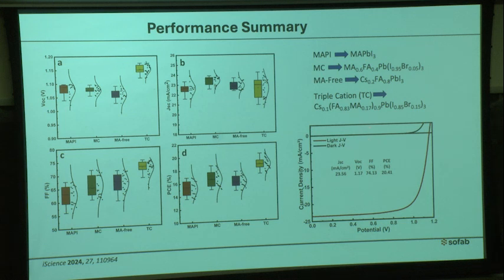Formamidinium will increase the stability towards moisture. If we add both cesium and formamidinium to the methyl ammonium, we can get perovskite with superior quality. That is due to improvement in quality of the perovskite, and we are able to get much higher power conversion efficiency as compared to other perovskite compositions. So MAPI means MAPbI3, and mixed cation is this composition, and we have different compositions.